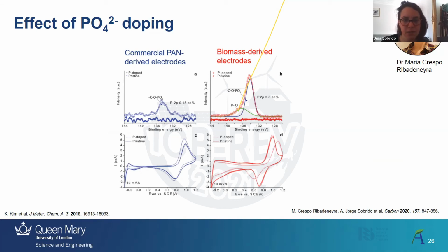So here what I'm showing is an XPS of the phosphorus line, where we can see this is the pristine commercial electrode, and this is the electrode with some phosphorus doping. The amount that we could introduce was really low compared to the amount that we could introduce in the case of our biomass fibers. It has to do with the fact that we are substituting some of the oxygen functionalities with the phosphate, and the oxygen ones were already low to start with in the case of the commercial fibers.